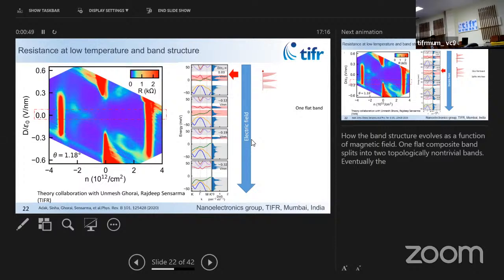Because you know the band structure very well. Here you don't even need to know the band structure per se. It's just the symmetry. You have 4-fold degeneracy, spin 2, valley 2, and that's it. You have a band which is full. That's the only thing. Details of the band structure are not even needed. You have a flat band, you just get filled or empty. You just need a gap above that band.